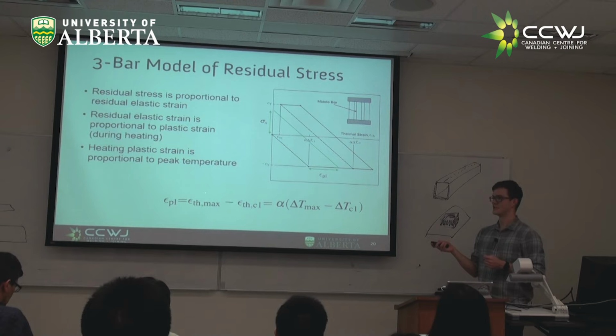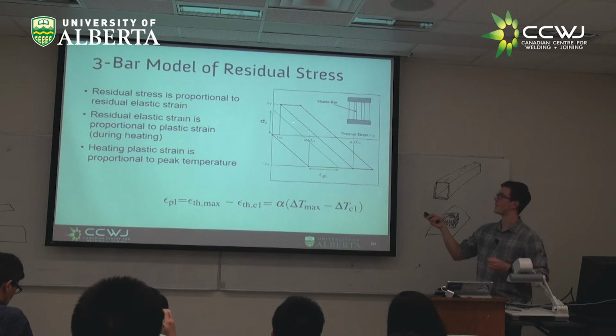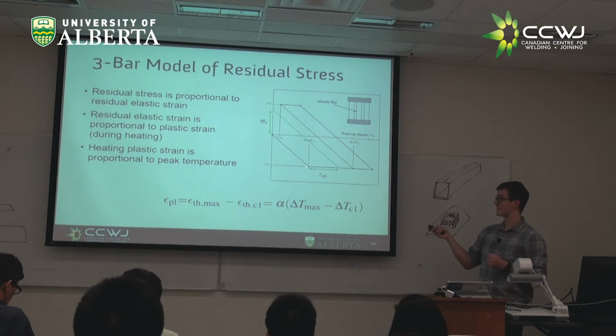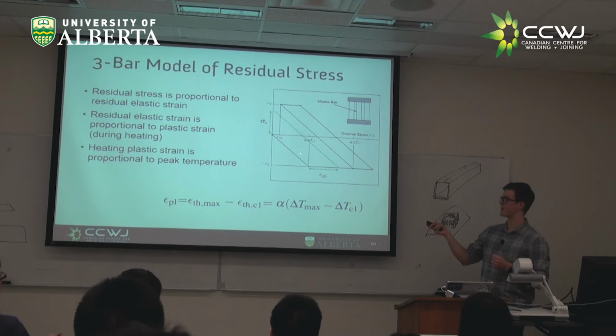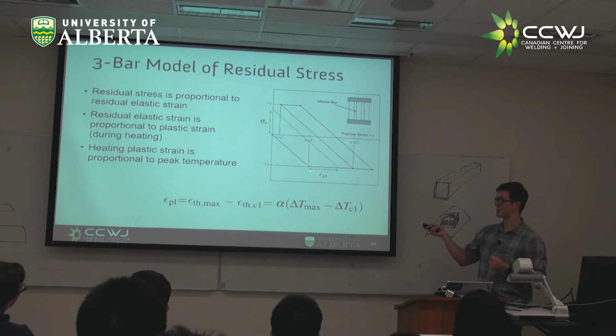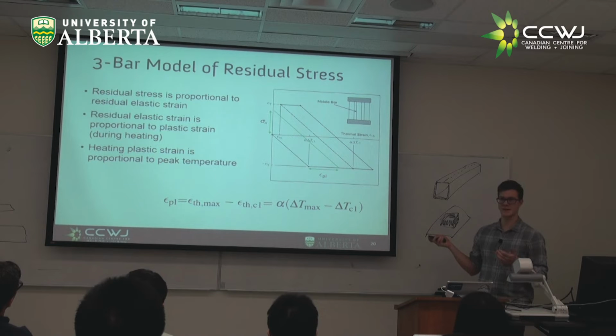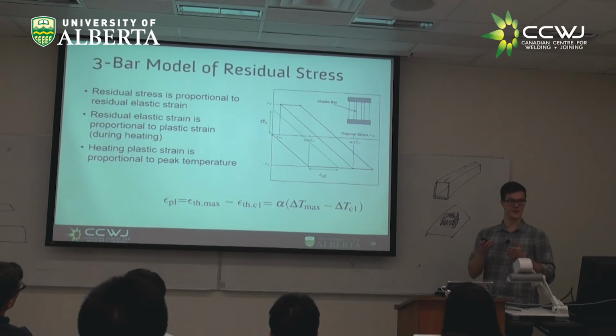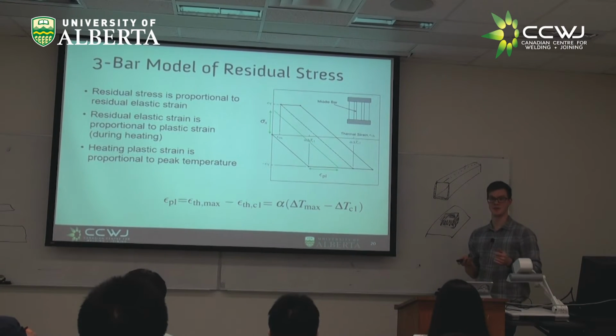Now, just to reiterate what we went over. Residual stress is going to be proportional to our residual elastic strain, which is where we are in this axis. Our residual elastic strain is proportional to the amount of plastic strain we have, how much we heat above this point. And our plastic strain is going to be proportional to our peak temperature. So we can end up with this simple expression where our stress equals elastic strain, our elastic strain is going to equal plastic strain, and our plastic strain is just how high we heat above this point. So if we know this temperature, about 80 degrees above room temperature for structural steel, and we know our peak temperature distribution, we should be able to plot for every point in our weld how much our residual stress is going to be.